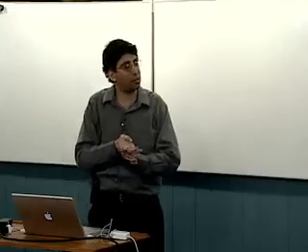And so there is a question about what the role of water is. That is, when those cations that are going in and out are out in solution, they have a certain number of waters in their first and second coordination spheres. But you also must realize that when they go into that lattice, they can't take all those waters with them. There's not enough room in there to take all the waters. Well, maybe cesium. Cesium is supposed to have 1 water, so it could probably bring that if it wanted to. But lithium is supposed to have 12 waters that it likes to carry around with it. That's not going to fit in. Even sodium with 6 waters is not going to fit in. So what's the role that the water is playing?